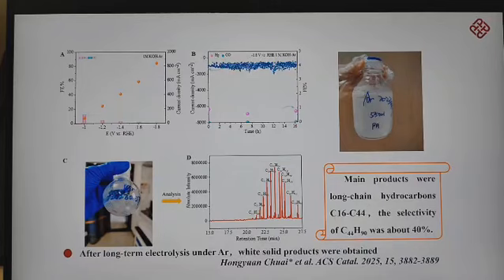To verify whether the obtained long-chain hydrocarbons were products of CO2 or not, we conducted experiments under the same conditions in argon and obtained similar white products. The white product in a blue-capped bottle was obtained from the electrolyte. This result indicated that the long-chain hydrocarbons were not the products of CO2 reduction. They are the products of the hydrogenation of the carbon-based electrode. The above results demonstrate that carbon materials can undergo a hydrogenation reaction under ambient temperature and pressure to produce high-carbon products.